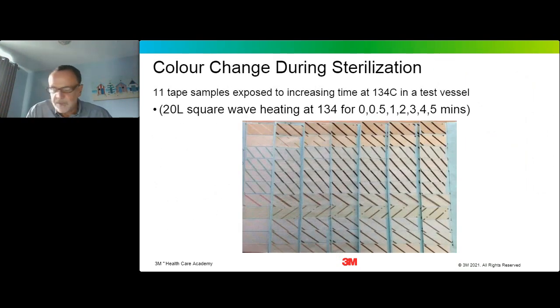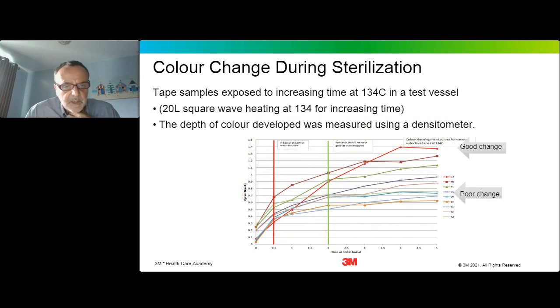So if you look at this slide, you can see a number of samples of autoclave tape from different manufacturers that have been exposed anywhere from 0 up to 5 minutes at 134 in a steam test vessel. And you can see from this picture how the autoclave tapes will change colour as they are exposed to different lengths of time of exposure. And we can also quantify those colour changes using this densitometer. And if we plot the optical density of the measured colour against time of exposure, you will get a typical set of curves like this, which are shown on this chart.